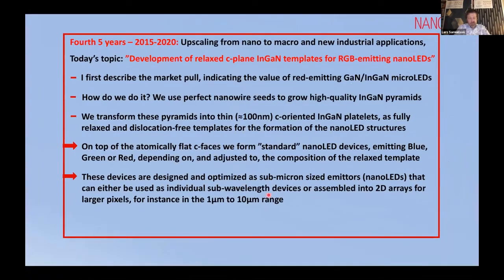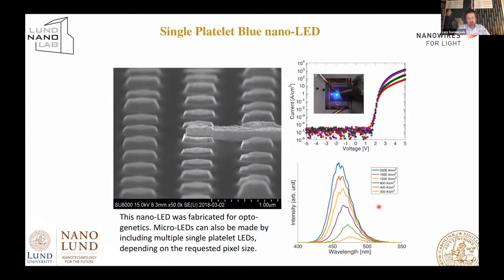So on top of these, you can then form more or less standard nano-LED devices emitting blue, green, and red, adjusted to the composition of the relaxed template. These devices are designed and optimized as submicron-sized emitters, nano-LEDs, that can either be used as individual sub-wavelength devices, or they can be assembled. So you can assemble a few of them for, say, 2-micron-sized pixels, or many more of them to make, say, a 10-micron pixel. So here's just an example.